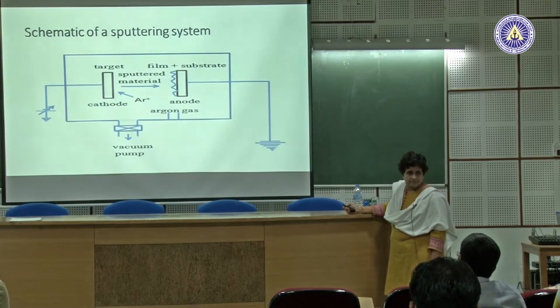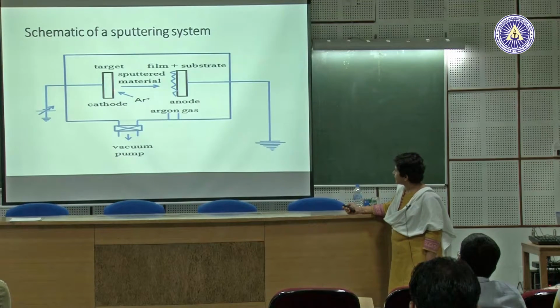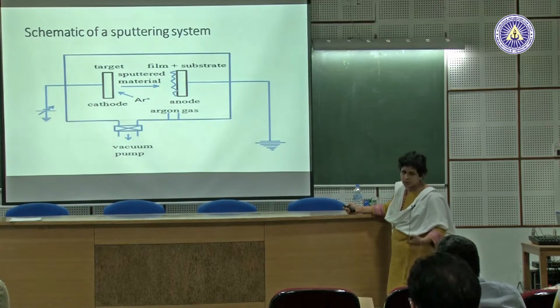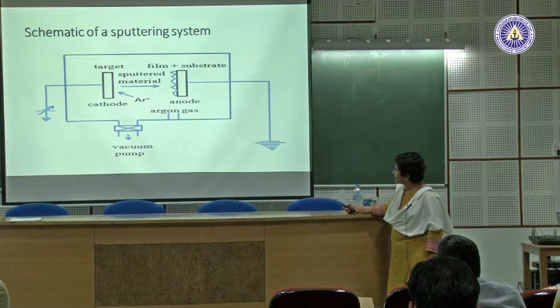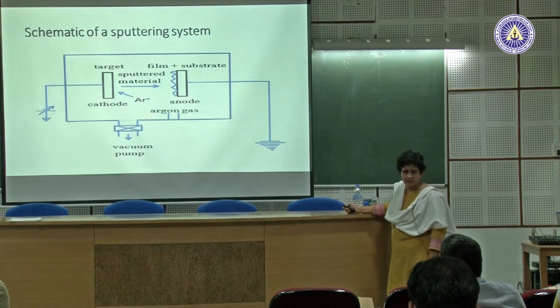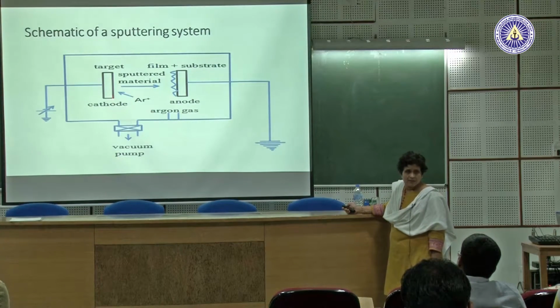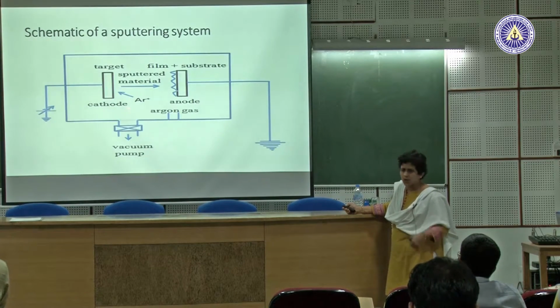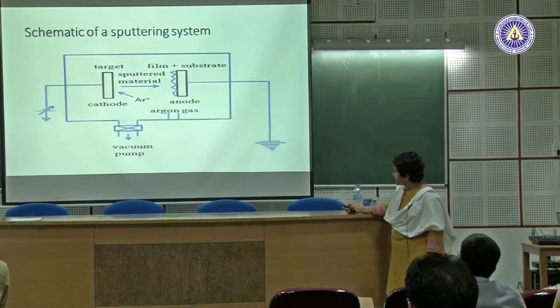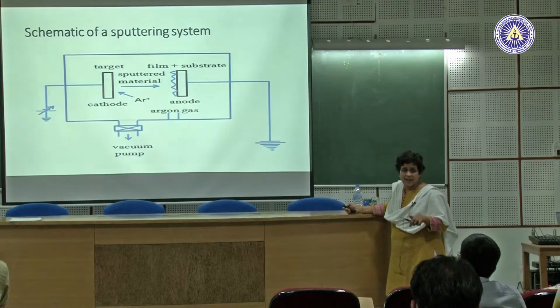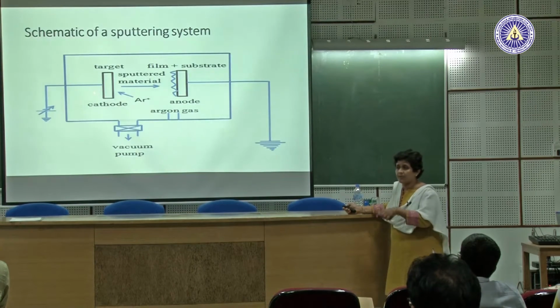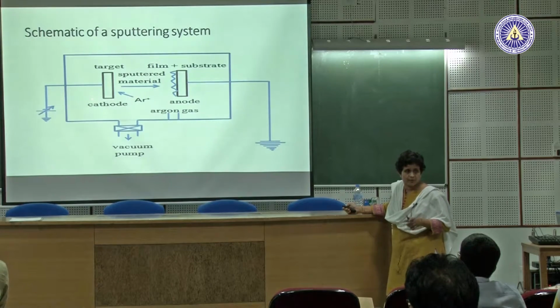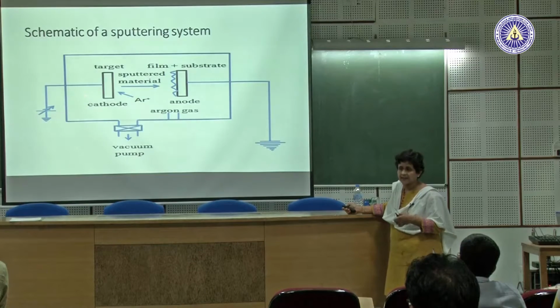Argon is the working gas which I put in the chamber, and then by applying the DC voltage or RF voltage, I create a plasma. The argon gas in this chamber is getting ionized to argon plus, right. Argon plus will be attracted towards the cathode, and it will hit the cathode at roughly the voltages which you apply outside, and generally voltages are few hundred volts here. Okay. So, they are hitting the target pretty hard. Since they are hitting the target pretty hard, they have enough energy that this argon ion can sputter off aluminum or copper that is there on the target. That is why it is called sputtering process. So, it is sputtering the target. Argon ions are hitting the target and they are sputtering the target.